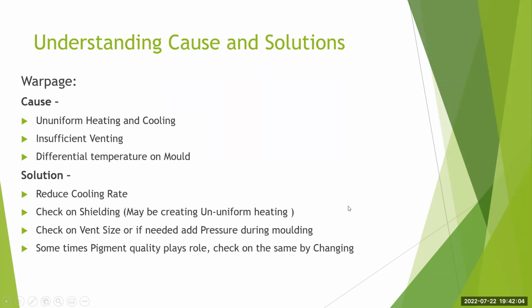Warpage is basically creating unwanted stresses in the product, along with non-uniform heating. So the first thing is that you need to normalize the heating. If you do a slow cooling, the heat in the mold as well as the product reaches equilibrium all over the part, and you get uniform heating, and the cooling becomes uniform. Your product also stabilizes very smoothly. Many things happen in the oven. Sometimes the mold is positioned in such a way that it gets uneven heating, higher heating on one part and lower on the other.